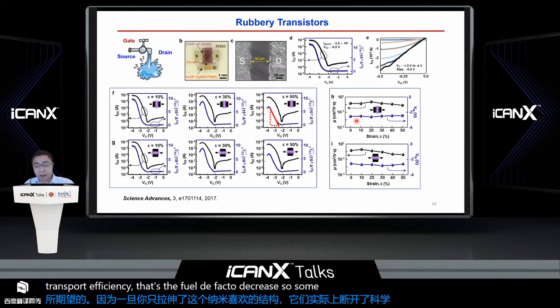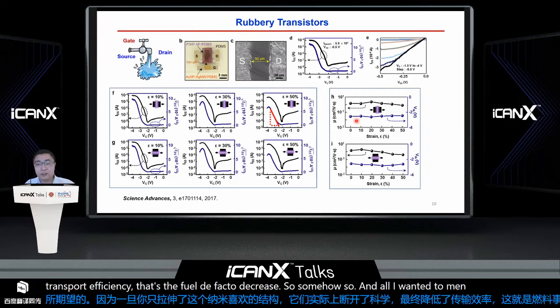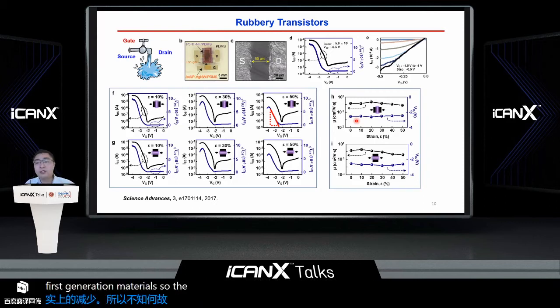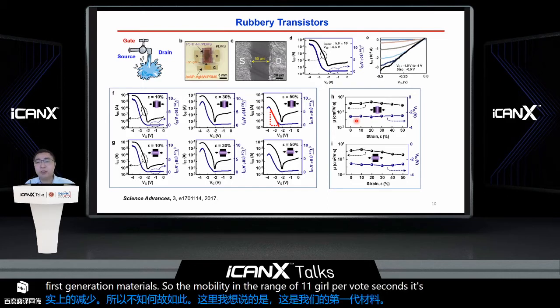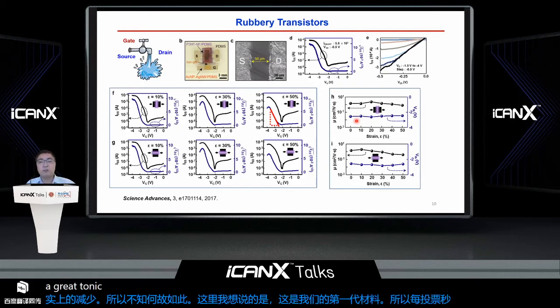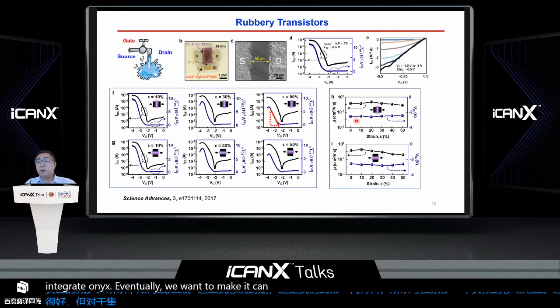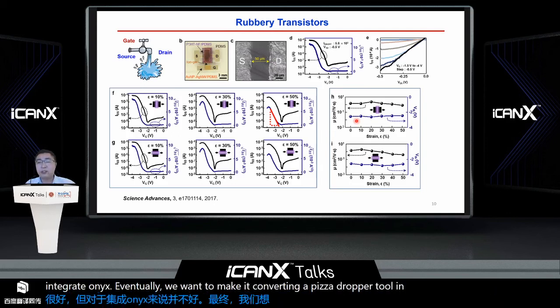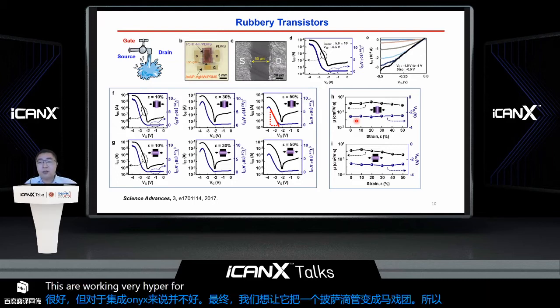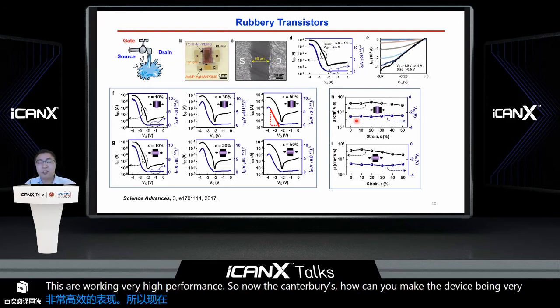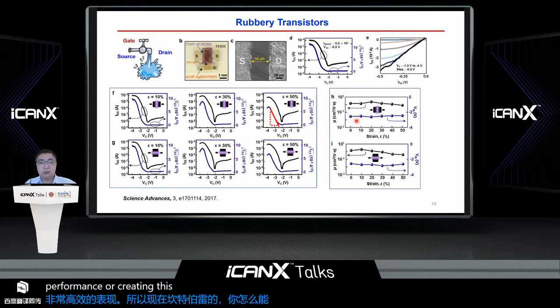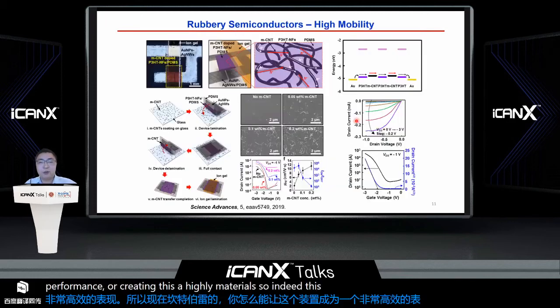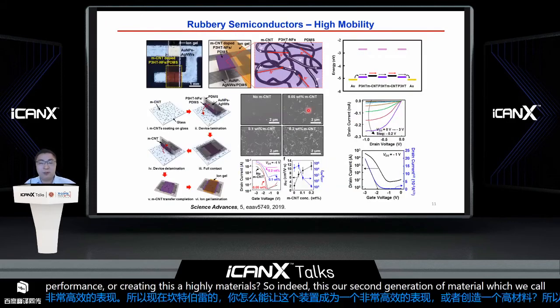I also want to mention that this is our first generation material, so the mobility is in the range of 1 centimeter square per volt second. It's good, but it's not great for integrated electronics. Eventually, we want to convert a piece of rubber to integrated circuits, so we want the transistor to work with very high performance. The challenge is how to make the device very high performance, creating high mobility materials. Indeed, this is our second generation material, which we call the high mobility rubbery semiconductors.